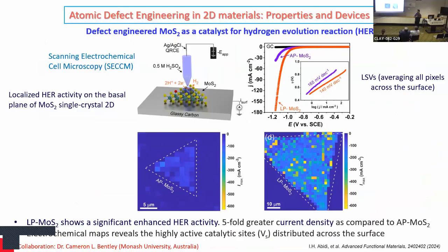Globally, people do HER testing and can find out the activity, but they cannot map it. In this case, because we have sulfur vacancy defects sitting on the surface, in the 2D maps we can clearly see that once we have defected MoS2, we have a higher amount of activation sites, or active sites, on the surface of MoS2 for HER activity.